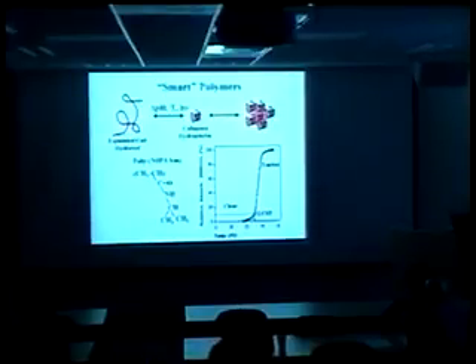Now, if you copolymerize NiPAM with more hydrophilic monomers, for example, such as acrylic acid, you can shift and control at what temperature this transition occurs, and that will also affect and sometimes broaden it out a little bit, so that rather than just a pure switch, you can also think about intermediate conformations between this and that.